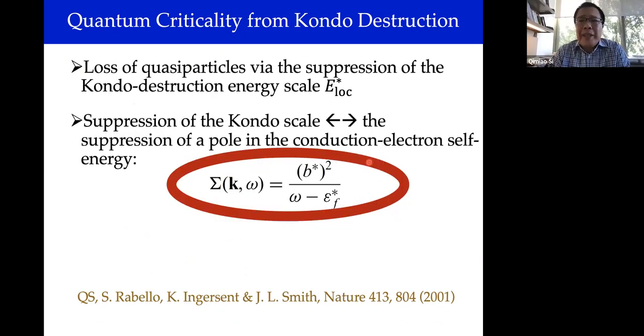And so one way to think about the destruction of the Kondo effect is that when the E star scale is non-zero, it shows up in the particular form of the conduction electron self-energy. This epsilon_F star is actually familiar. That's the basis of the renormalized bands picture. But the weight of this E star scale would show up in the weight of this pole of the conduction electron self-energy. And once you have a pole in the conduction electron self-energy, there will be, in the end, a single electron Green's function with two poles capturing the two renormalized bands. The mean field picture I already showed you earlier.